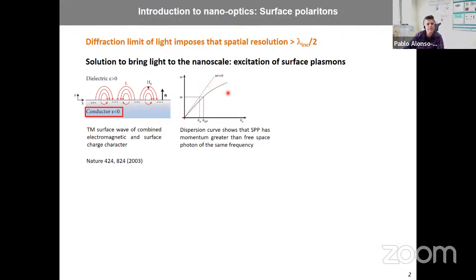Okay, and you can see that it lies to the right, meaning that for a fixed frequency omega, the momentum of these surface polaritons is larger than the momentum of the incident light. Momentum is 2 pi divided by lambda, meaning that lambda is smaller than the wavelength of the incident light. So these surface plasmons or surface polaritons work as funnels that permit to confine light to the nanoscale.